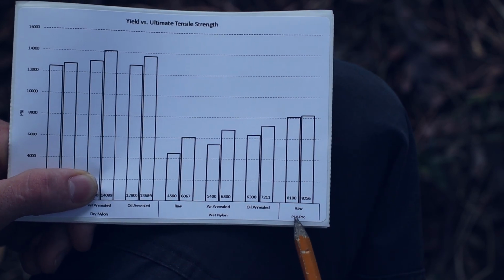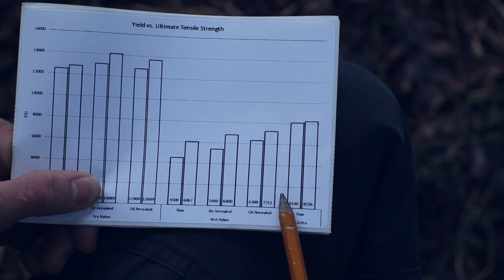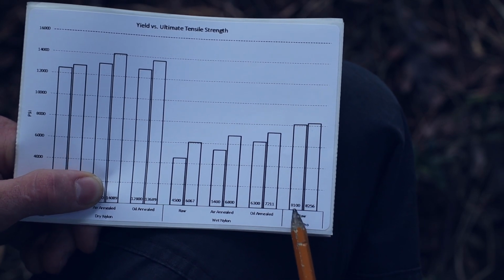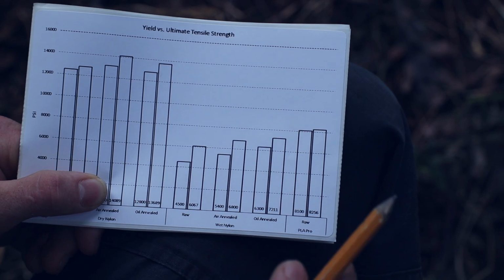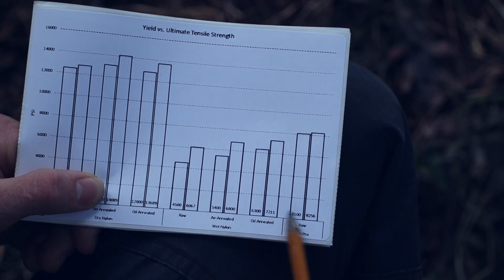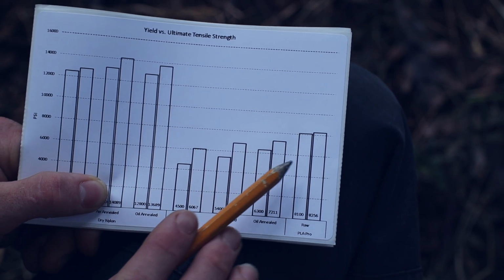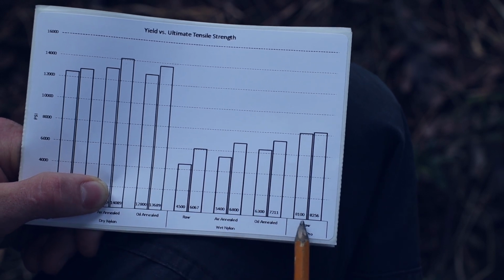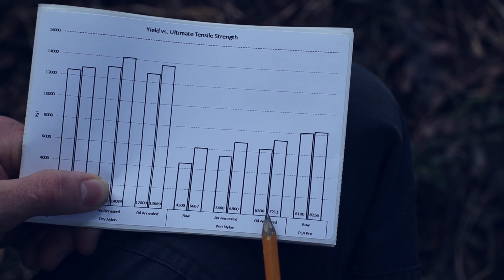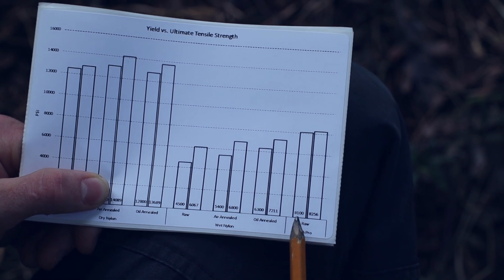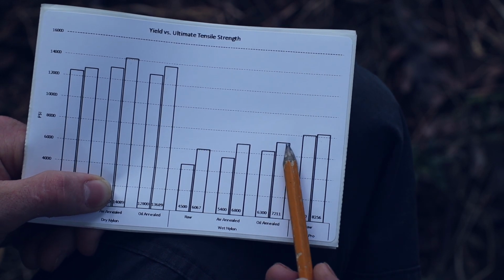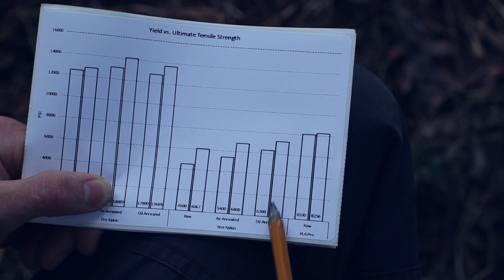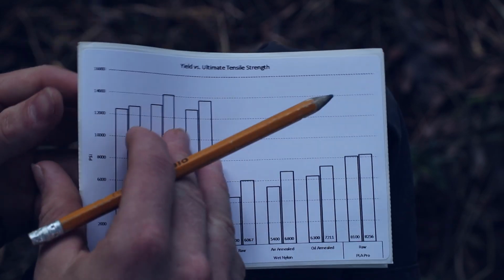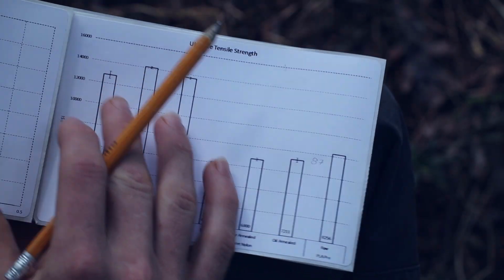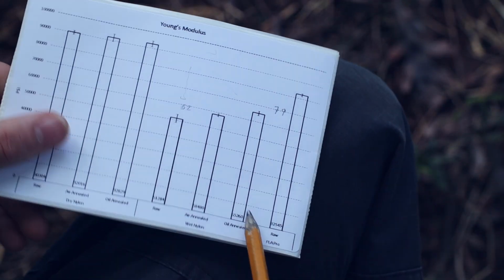Comparing all of these to the PLA Pro, it is actually very stiff right up to the point that it yields. There's very little of that plastic deformation zone, which is actually a good thing. And the PLA Pro is almost the same on yield and ultimate tensile strength at 8,100 psi. So we're looking at 7,200 compared to 8,100. The oil annealed is beginning to get up there to a practical level of strength. Not quite though, and it's still lacking significantly in the stiffness department. If we look at the Young's modulus again, we're still way behind on stiffness.